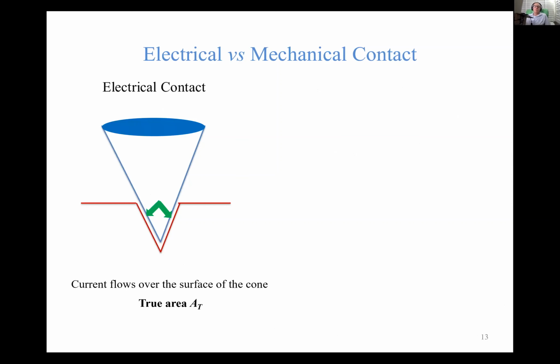So let me talk a little bit about some of the details of this model that you have to think about. The first thing is contact, and there's actually a difference between electrical contact and mechanical contact. On the left, I'm representing an asperity on the solid electrolyte with this blue cone, and it's indenting the red lithium, and it makes this indentation. And for electrical contact, the contact area that's relevant is the complete contact area of this sort of partial cone in this region, because the current flows over this entire surface of this little conical region. And so we have the relevant area we'll call the true contact area.